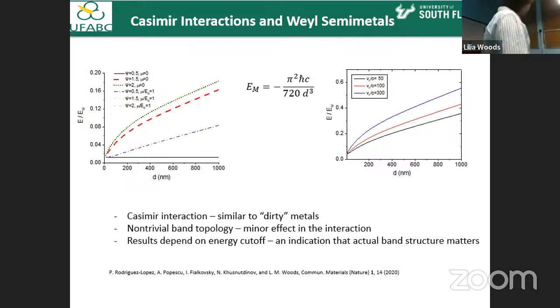And as you can see, the Weyl semi-metals behave like a dirty metal. No matter which parameter we change, the type of the material, the Fermi velocity, the characteristic behavior is the same. So it turns out that not only is the effect of the non-trivial topology small, it's now masked, it's covered by the typical electric response. A lot of technical work, but the payout in terms of Casimir non-trivial effects is small.